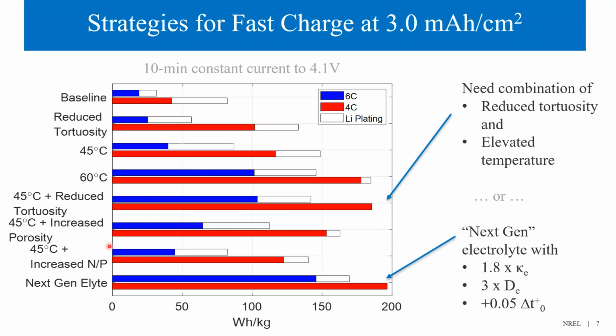Increasing the NP ratio is shown to be ineffective, and increased porosity is only marginally effective due to loss of overall energy density. For a loading of 3.0 milliamp hour per centimeter squared, a combination of operating at 45 degrees Celsius with reduced electrolyte tortuosity can enable energy densities of 186 and 104 watt-hour per kilogram during 4C and 6C constant current charge, and it can be a viable near-term technology. It's also important to continue research on next generation electrolyte.